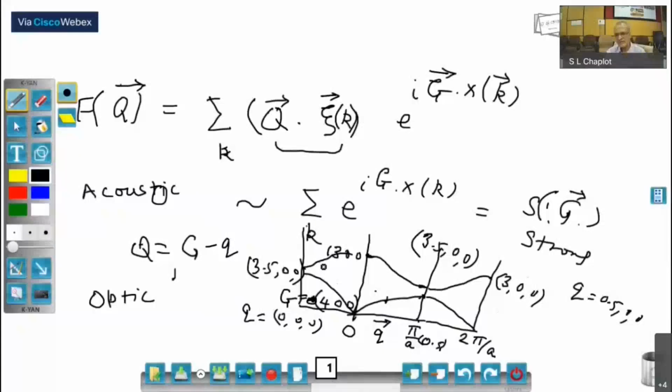So the idea is that we can continue phonon dispersion measurements from zone center to zone boundary, from zone boundary to another zone center on a different branch, and so on. This kind of thing is often done if the phonon eigenvectors vary very smoothly across the Brillouin zone.